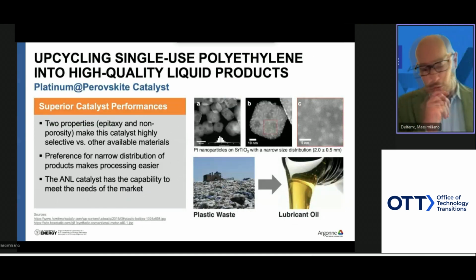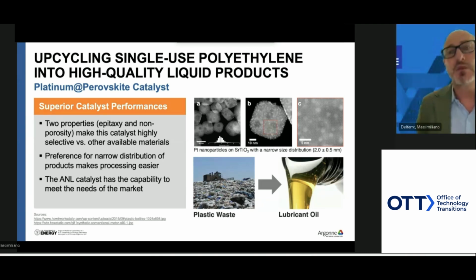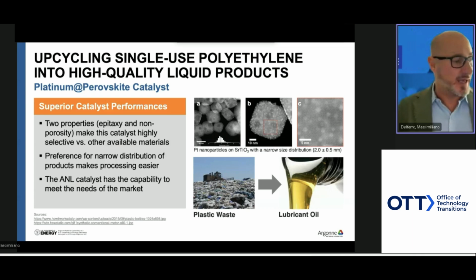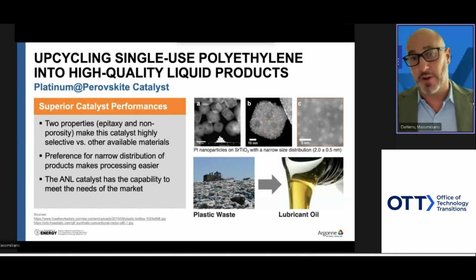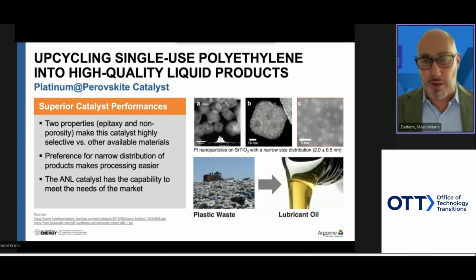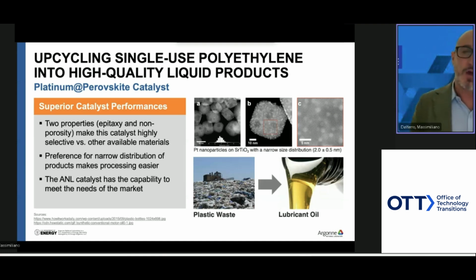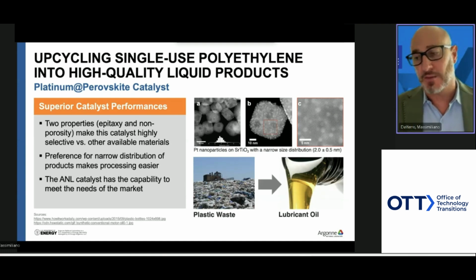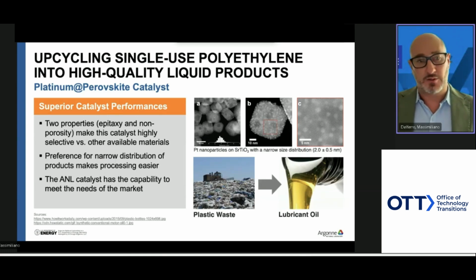This is where our initial discovery came in, roughly in 2016. We were interested in using a catalyst made of perovskites. You can see in these pictures, these are nanocuboids of perovskite, and we deposited platinum nanoparticles through a chemical process. Because the platinum and the perovskite support have the same crystal structure, this catalyst is very, very robust. I will show you later some examples of these characteristics and why they are important, particularly for transformation of plastic waste to lubricating oil.